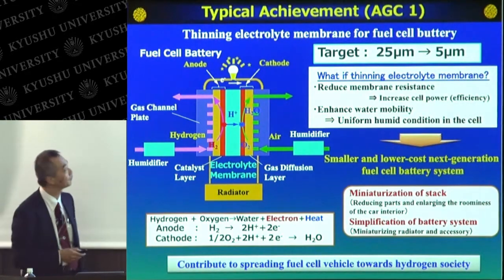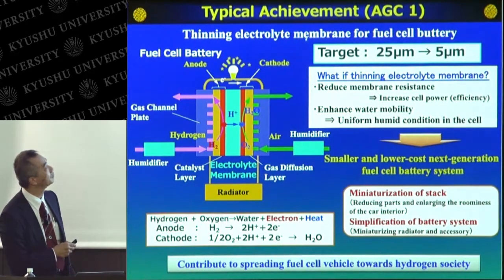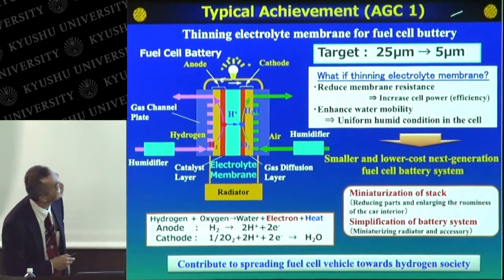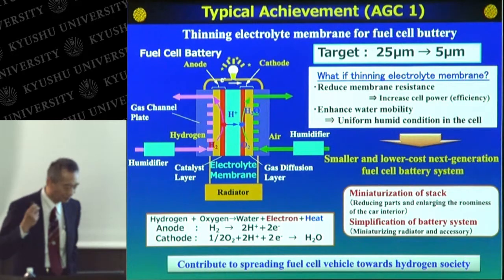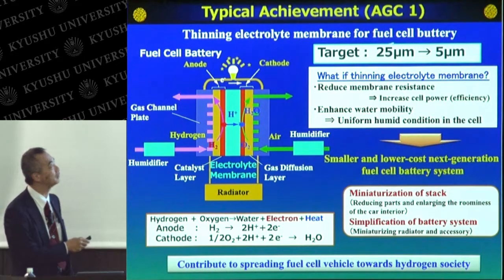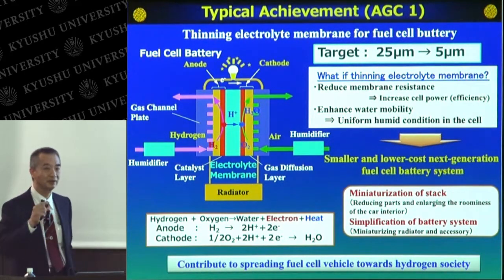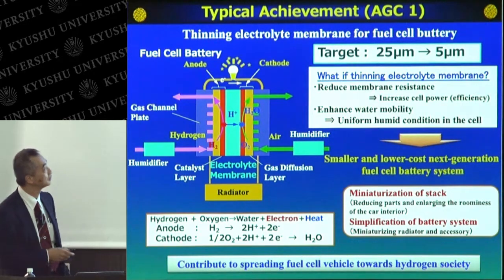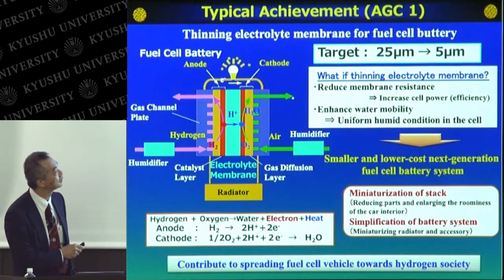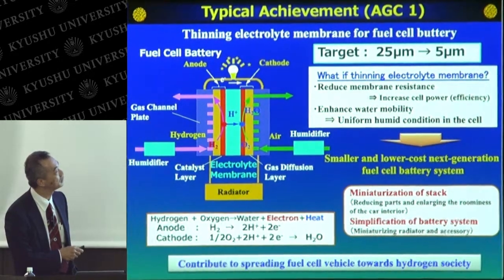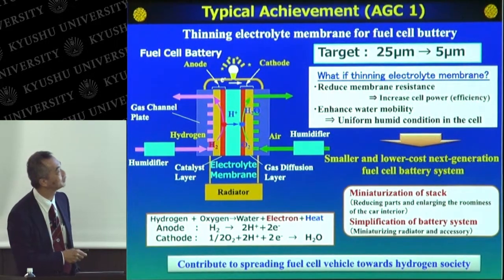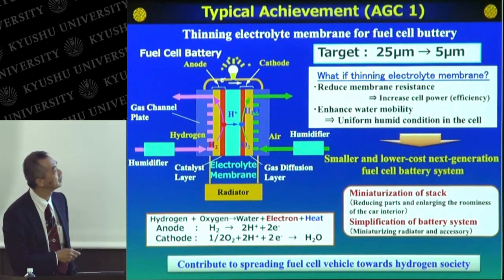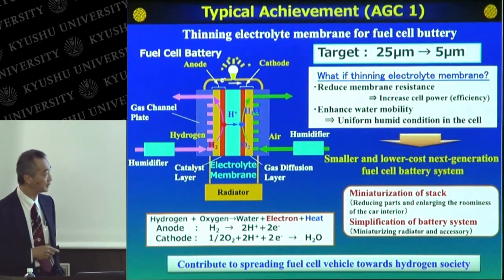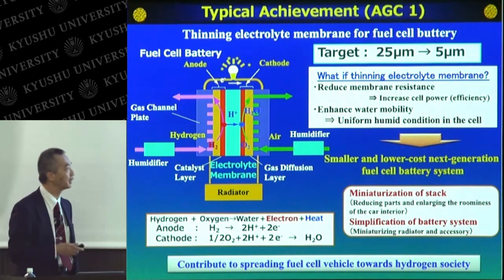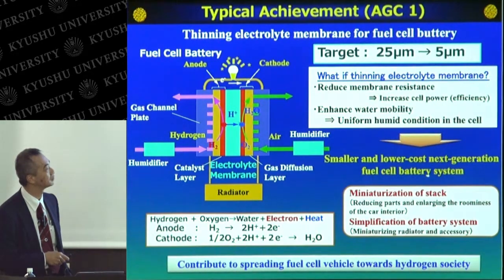Okay. Next, I'd like to show you the achievement from AGC. AGC's target is a thinner electrolyte membrane for fuel cell batteries. The target is to reduce the thickness from the conventional 25 micrometers to 5 micrometers, about 1/5. Such a reduction decreases the membrane resistance, which increases cell power and cell efficiency, and it also enhances water mobility, which realizes a uniform humid condition in the cells. So finally, such a thinner membrane realizes a smaller and low-cost next-generation fuel cell battery system.